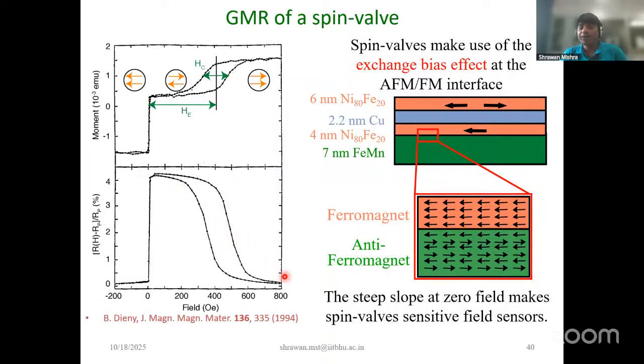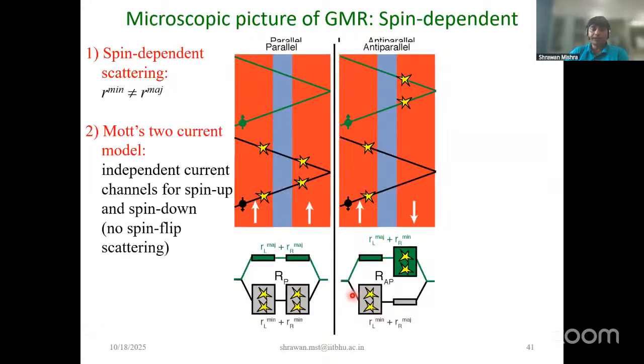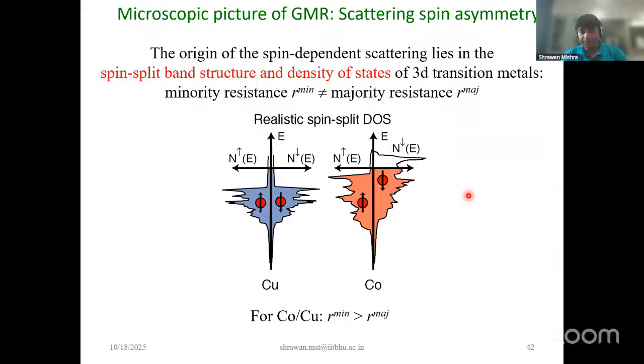And if you compare to the magnetic hysteresis that a generic ferromagnet shows, it is always zero-centered and symmetric, going to the same value in negative saturation as the identical value in positive saturation. But here, if you see the entire device magnetization, it is completely different due to the interfacial coupling of the two ferromagnetic materials. And that's again how this model predicted the resistivity due to spin-dependent scattering. So R parallel and R anti-parallel configurations give a huge change in the resistance of the various materials.